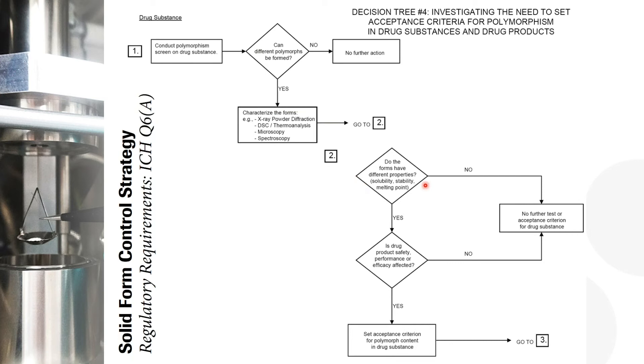But then, I like this statement here because it's a really philosophical question. Do the forms have different properties, solubility, stability, melting point? Yes or no? And to be honest, I always struggle with this question because, I mean, they have different crystalline forms. They have different crystal lattice and their hence lattice energies. So of course, they will have a different solubility value. It might be very similar, but it's different by definition. But if it's different, does it make an effect on the product safety performance or efficacy? In some cases, you would say no and then also no action is needed. But if yes, you need to set an acceptance criteria.